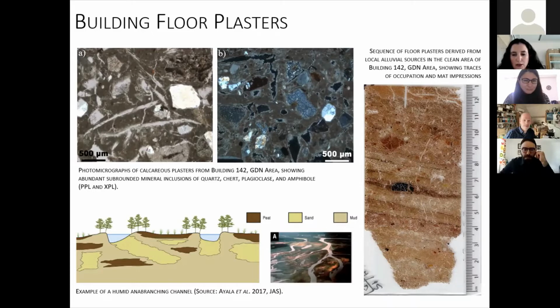This increase in the sand content of construction materials from the later levels of occupation has been hypothesized to stem from a shift in the exploitation of specific areas within the immediate landscape around the site, which was becoming increasingly drier during this period. This would imply that the extraction of fine-grained alluvial soils for the manufacture of architectural materials, those with the highest agricultural potential, was progressively abandoned to allow for their cultivation.